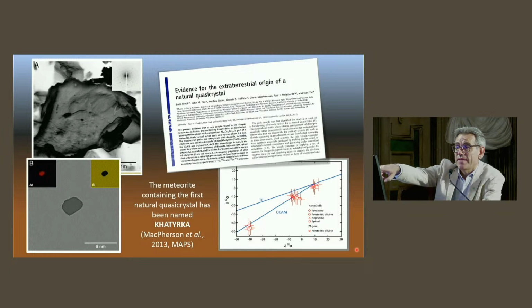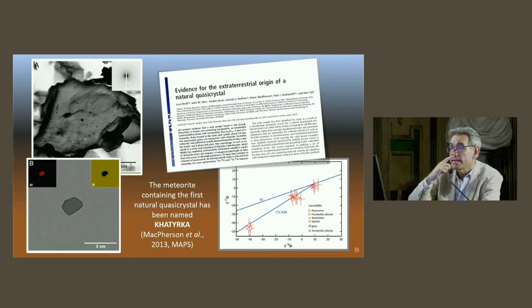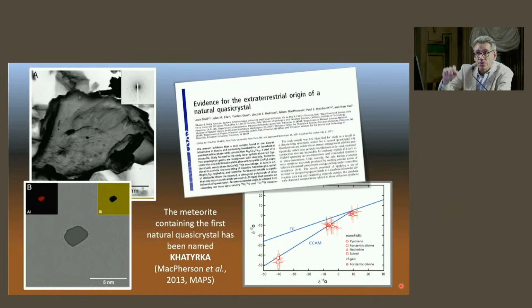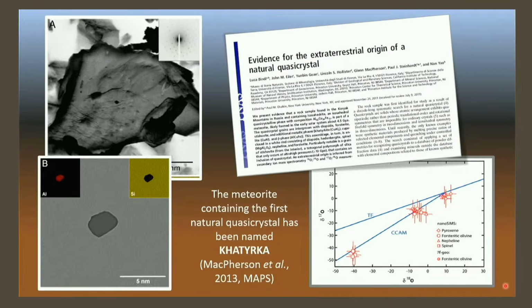More importantly, the 50 nanometer size stishovite grains contain inclusions of quasicrystals. And this was actually very important to individuate a strict relationship between a stishovite grain and the Florence Museum sample.